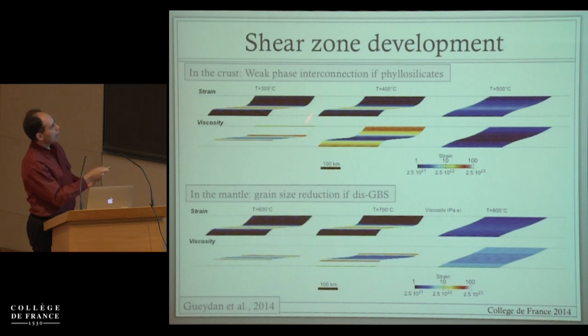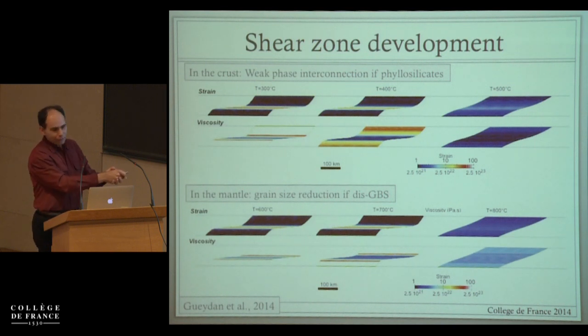And so shear zones happen from different processes. This is for crustal type of rheology, and really the key there was the formation of an interconnection of a weak phase, if that weak phase happens to be phyllosilicates. And here for the mantle type of rheology, we got these shear zones formed if you enter a certain deformation regime called dislocation accommodated grain boundary sliding, dis-GBS, excuse me for the shortcut there.